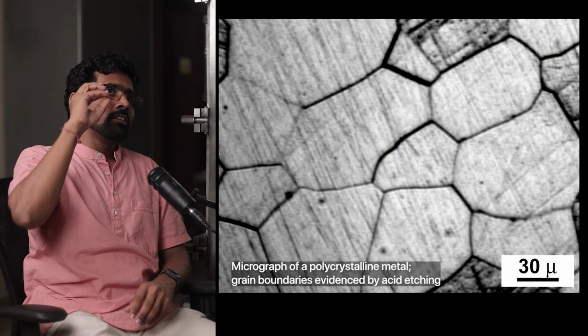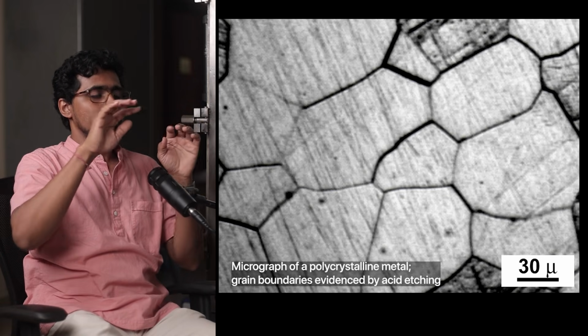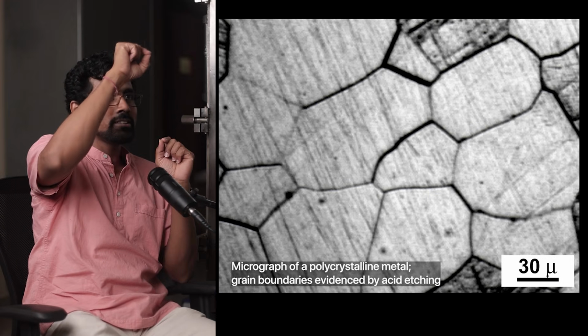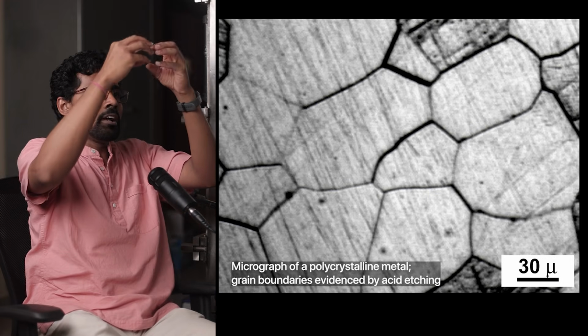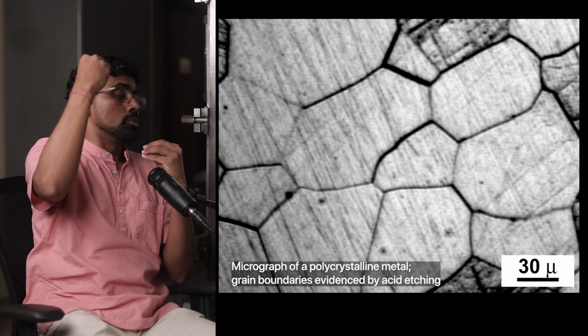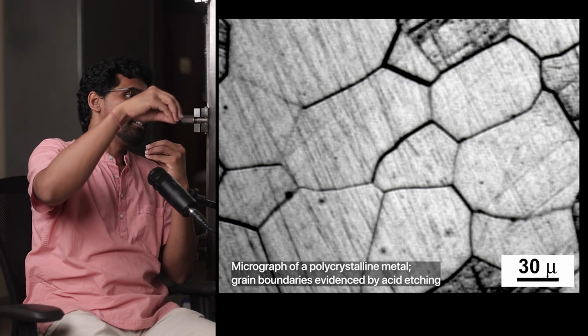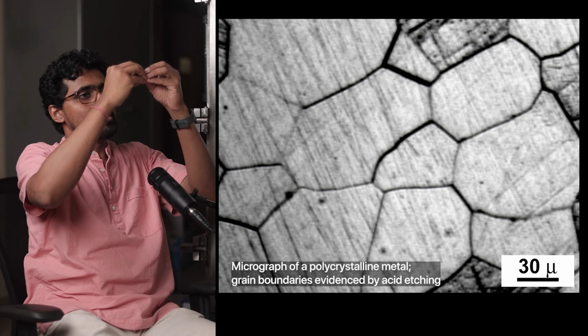If it's a normal columnar growth, you can see it right from the beginning till a large distance. If it's a polycrystalline growth, then in a liquid you have something growing. But if there are certain sites where the atoms can come and combine, those are called nucleation sites. Those could be any impurities in the liquid, and they act as nucleation sites. Some solid will form there, and then it would start growing outward in all directions, based on what sort of symmetry it follows while growing. So you can have 6-fold symmetry, you can have 4-fold symmetry, and the structures look really beautiful.